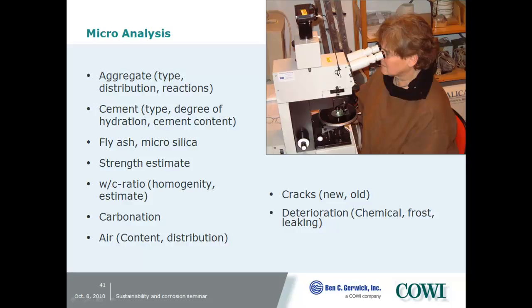But that's not necessary. I mean, you could still have load-dependent cracks that don't go through the aggregates, right? I would not expect so. But there is an example from this morning where you said the aggregate was so strong that it doesn't go through. Well, of course, there are cases where the aggregate is so strong. Yes, and in fact, that's one of the big things with seismic. You get some aggregate interlock, so the cracks go around the aggregate.